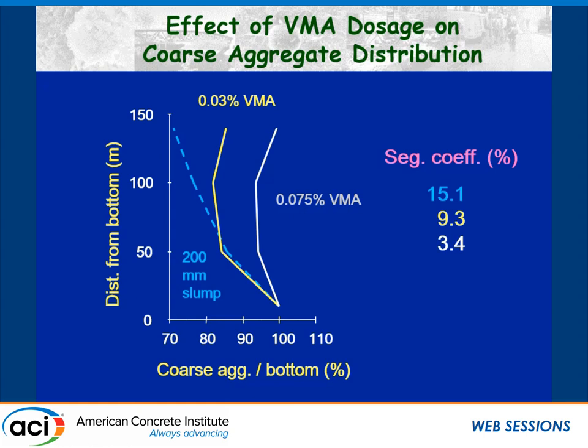So at the top, you have about 30% less coarse aggregate than the bottom. Obviously, you have segregation. And then this is a viscosity modifying admixture low dosage. You have similar behavior. And the high dosage, you have almost no segregation. So the lower the segregation coefficient, the more stable the concrete is.